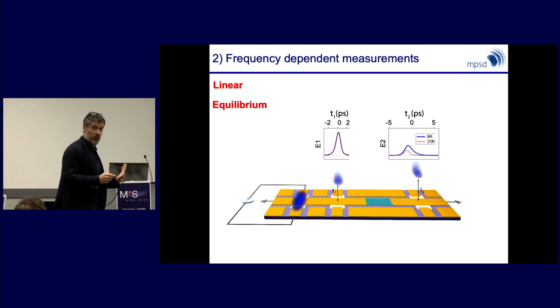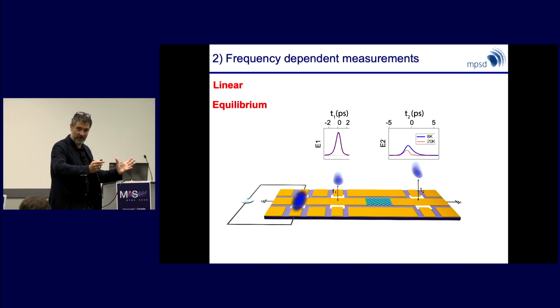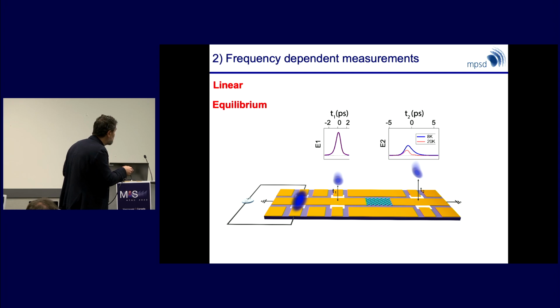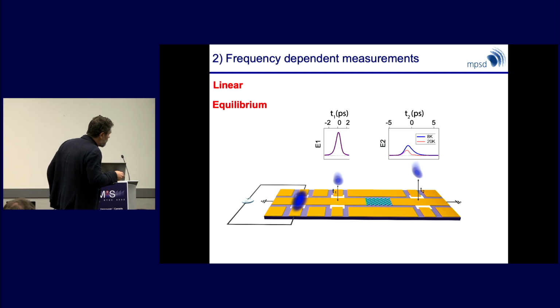So now to the workhorse of the measurements. Here you put the C60. Now you want to have three Auston switches. One, which is a big one, launches the current pulse. Then a second one samples the incoming pulse as it's coming in. I want to calibrate the time, shape and intensity of the incoming current pulse. These are typical measurements. Then this current pulse will go through, or it will get reflected, and at the second Auston switch, I can measure the transmission.